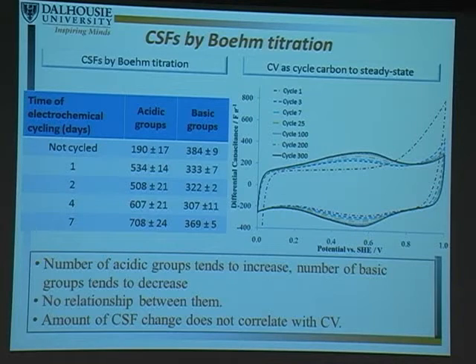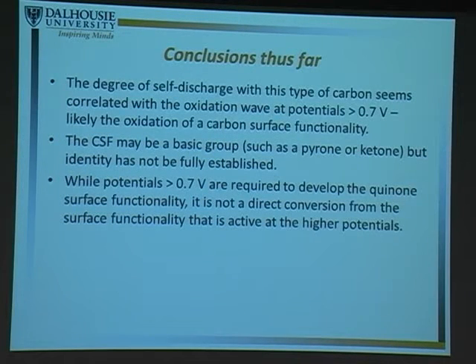And so with this Boehm titration, what we determined is that because it's an ex situ method, we couldn't get anything really out of it. It wasn't telling us anything about the electrochemical surface functionalities. So at this point, we really don't know what is going on with these guys. And so for this work, it's still continuing, but we're really trying to figure out how do we identify those surface functionalities? How do we split apart that development of the quinone, which is in that oxidation wave, but we also believe that some of that oxidation wave is actually the carbon converting to carbon monoxide and carbon dioxide. And so currently we're trying to separate those processes out.